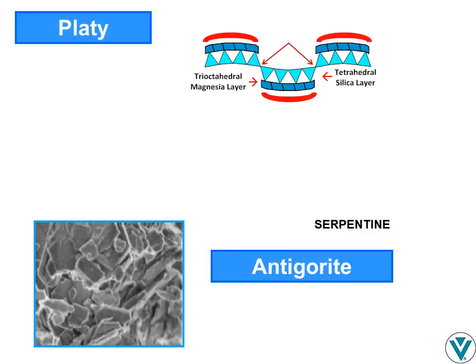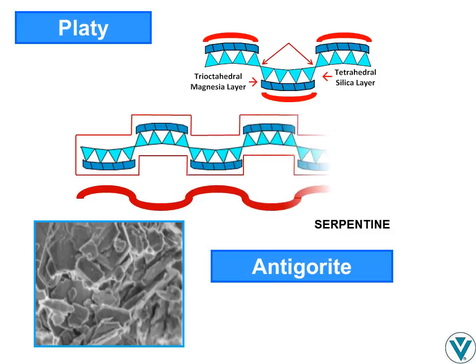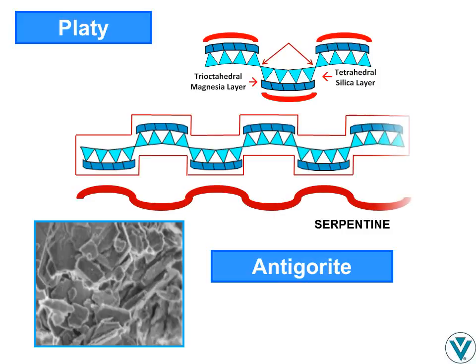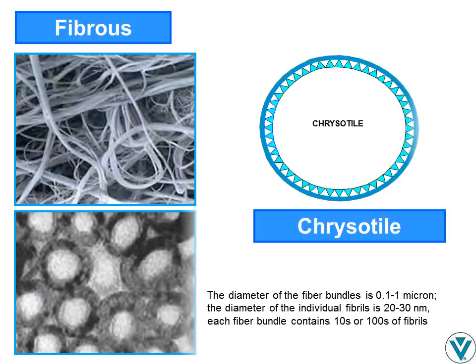A magnesium-based analog of kaolin is the serpentine mineral antigorite. The antigorite sheet structure does not directly correspond to that of kaolinite, however, because the tri-octahedral layer is an even poorer fit for the silica sheet. This mismatch is compensated by stretching of the apical silica oxygens so that they can form the common oxygen link, resulting in structure bending. Antigorite crystals are platy because the tetrahedral silica layer remains continuous, but only by periodically rotating 180 degrees. This prevents continuity of the octahedral layer, so the face of an antigorite platelet is corrugated. When both the octahedral and tetrahedral sheets are continuous — that is, with no inversion of the silica layer — the octahedral-tetrahedral mismatch causes continuous bending into long tubes, resulting in the asbestos mineral chrysotile.